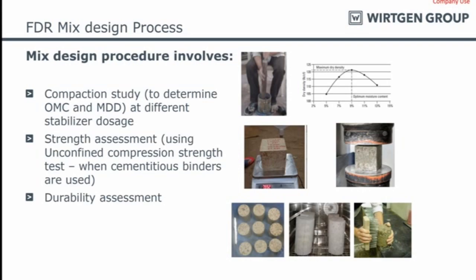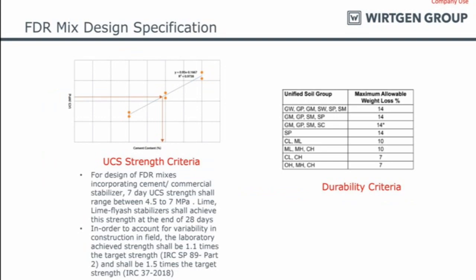Then we need to cast 150 mm cubical specimens at your maximum dry density as well as OMC at each of your cement contents to determine the UCS, the unconfined compressive strength, at the end of 28 days. Then we need to perform 12 cycles of the wet-dry durability test on each of the specimens at their estimated cement content. Here we find your maximum allowable weight loss. Finally, we plot a graph of your UCS and your wet-dry durability results to determine your desired cement content. So this is how we fix the cement content for the project.